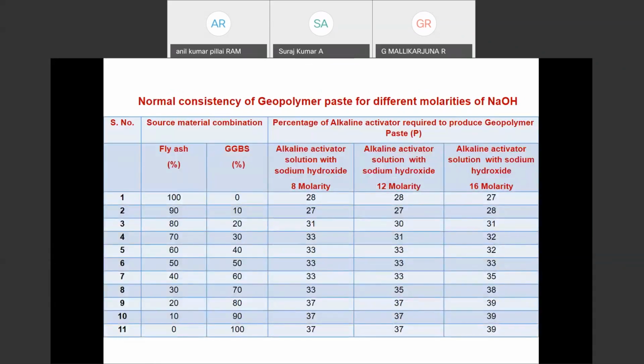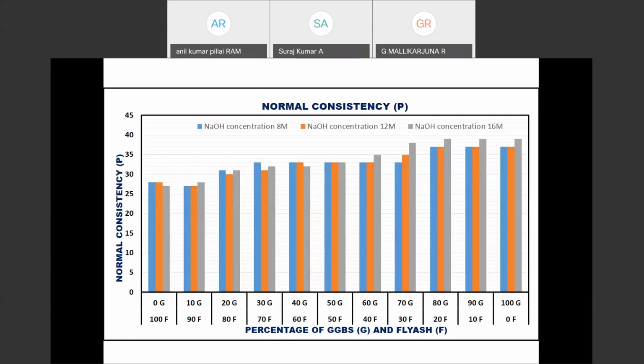And here, for the normal consistency, we have done the work for 8 molar, 12 molar, and 16 molar. We have taken fly ash ratios from 100 to 0. After 50% fly ash, there is not much effect on the normal consistency of those combinations. And one more thing: whenever we increase the concentration of sodium hydroxide, the normal consistency values also increase.